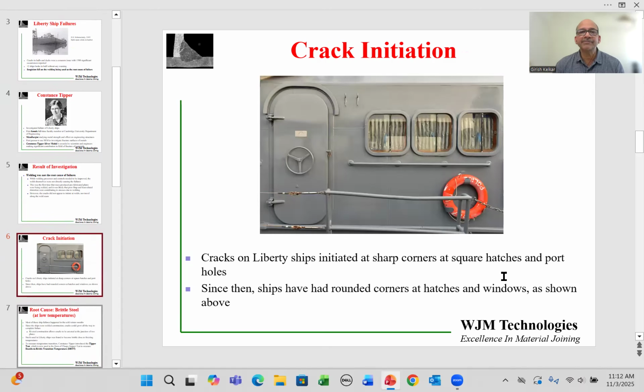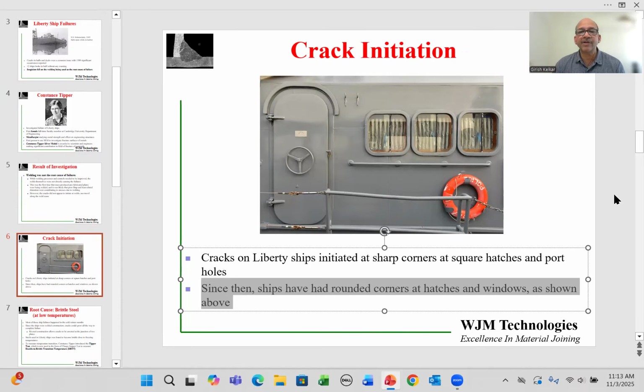So where did the cracks initiate? The crack initiation was found to happen at sharp corners, at square hatches and portholes. Back in the day, these square hatches or door frames and portholes had sharp corners, and these sharp corners resulted in being stress risers, and under the right circumstances, a crack would initiate from these locations. Since the Liberty ship disasters, all ships now have rounded hatches and ports as shown in this picture above. I could not find a picture of the square hatches and round ports from the Liberty ship era itself.